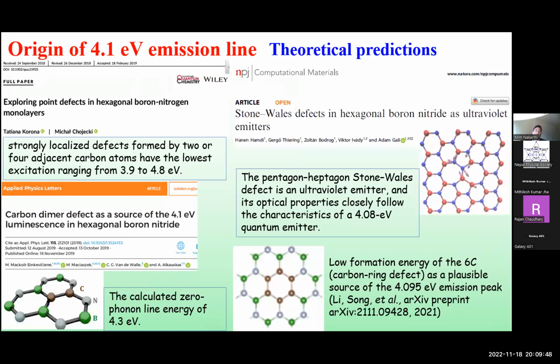All right, so the next question is definitely what is that defect, and what is emitting that sharp, atomic-like emission in the UV range. There is a lot of computational theoretical work, and they have predicted what could be the origin of that 4.1 eV. Most of the work is done in first principle calculation, and they have predicted that this should be related to carbon-related defects, which depend on where the carbon is sitting and how many carbons are sitting in the boron or nitrogen site.